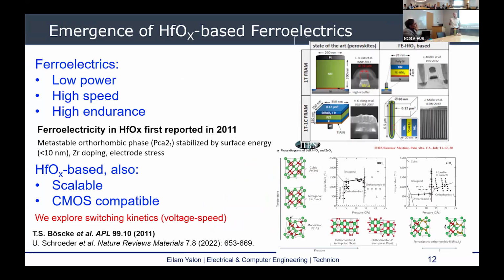Now, ferroelectric materials and memories have been known for a while, for over a decade, but still we don't use them. I showed earlier that we're using flash and DRAM, and we don't use ferroelectric memories in high volume in our devices. One of the main reasons is that the ferroelectric materials known to us until not too long ago, some perovskites, are not CMOS-compatible, and they couldn't be scaled below roughly 100 nanometers. They don't show ferroelectricity generally below about 100 nanometers, so they have very limited integration and limited scaling.